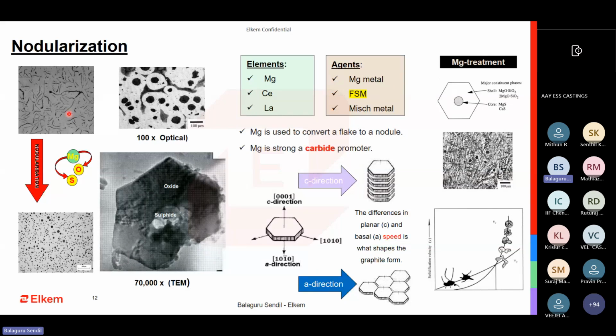Multiple options are available, but the key takeaway here is that magnesium is not very good when it comes to the casting properties. These are extremely carbidic. If you take this image on the extreme right, after ductile iron treatment, you have just created the nuclei. You don't have any nodules formed. It is more or less full of carbides. After ductile iron treatment, you can pour a sample before adding inoculant and see how much nodule count you have. You hardly see nodules, and it is full of carbides.